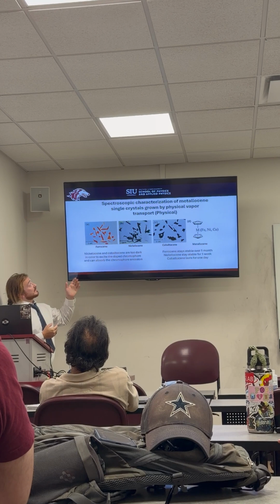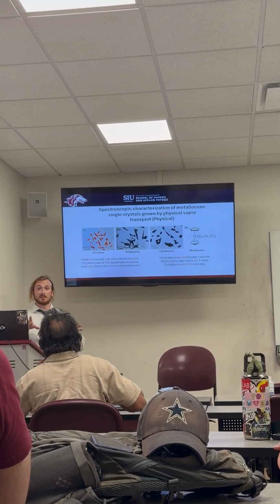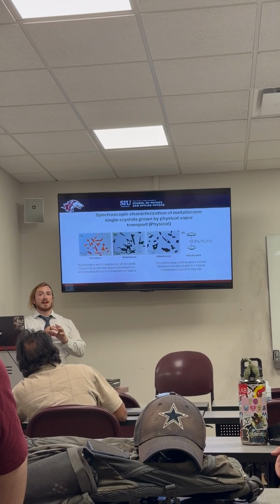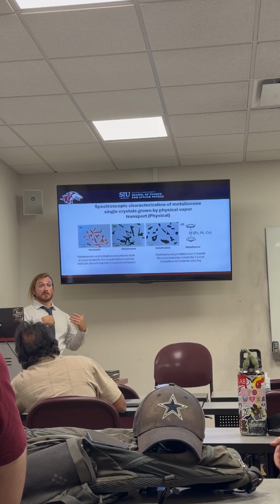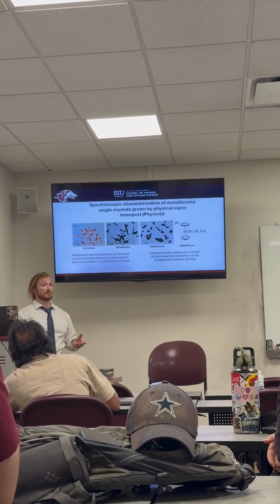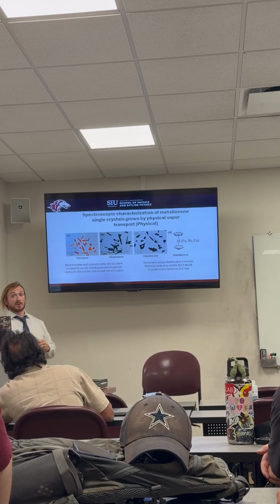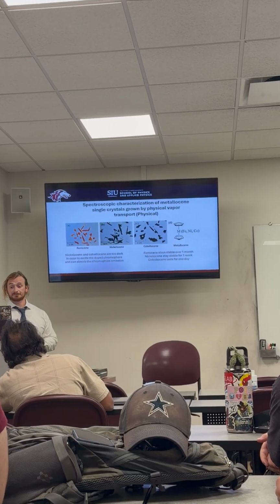Ferrocene, although this picture does not quite do it justice, is more translucent. You can kind of see through it in this case. And also the ferrocene is more naturally colored, like it's orange, and chromophores, as you remember from the previous slides, are orange to reddish. When you mix them together, the absorption is going to be mainly from the chromophore, and it's going to be emitted from the chromophore. In other words, the ferrocene is not going to absorb this.